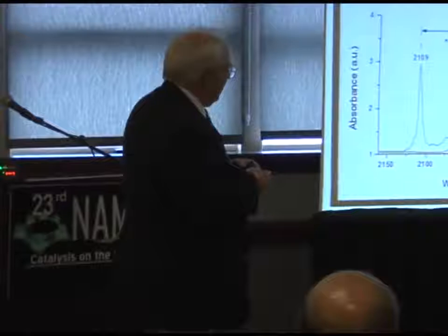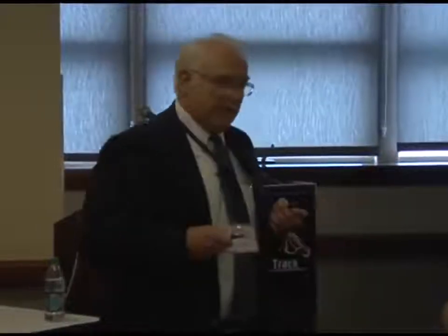And what you see is the frequencies are different. One can analyze the spectra in a conventional way and see the support effect as a ligand showing up in the frequency of the carbonyl bands and confirming that the MgO is a good electron donor ligand, whereas the HY zeolite is not a good electron donor ligand.